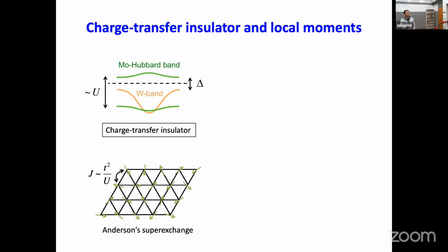The basic idea is actually we go back to the charge transfer insulator before band inversion. Then the strong correlation will open up a Mott gap for the Moiré layer. Then you bring the tungsten selenide band closer to the lower Hubbard band of the Moiré layer by an electric field. Then at filling factor 1, the Fermi energy is here. Then the Moiré layer will actually support a triangular lattice of local moments because it's in a Mott insulating state.